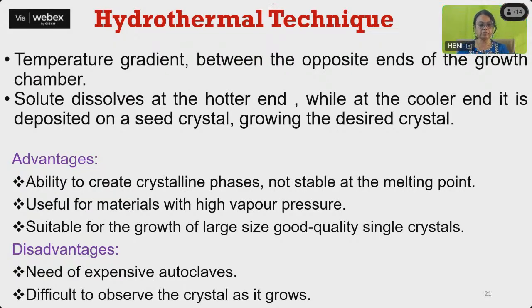So the advantage is that it can produce crystalline phases which are not stable at the melting point. Some crystalline phases are not stable at the melting point, or there is a phase transformation. It is also useful for materials with very high vapor pressure, because it is grown under pressure, and suitable for large size crystals. But the disadvantage is that you require an autoclave.